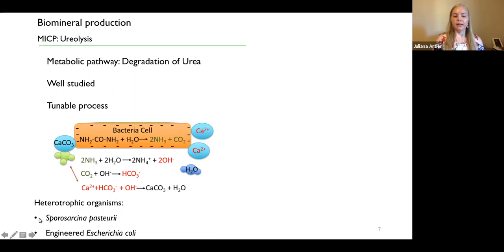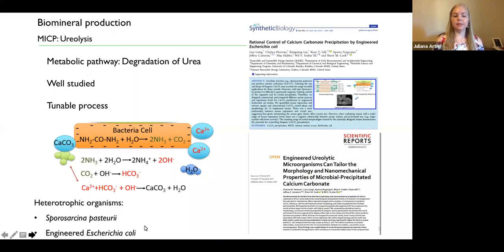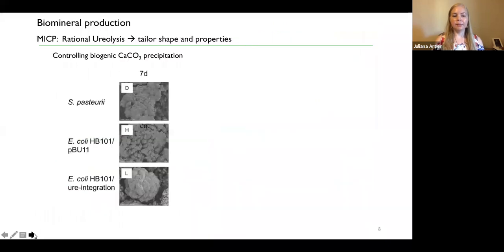...species that can produce spores and survive in extreme environments is a well-studied one. But we also studied some of the changes on an engineered strain that received the operon from the spore-forming species, where we saw that we had good nanomechanical properties by simply changing how much calcites or calcium carbonates can be precipitated by modulating the expression of the enzymes in the organisms.